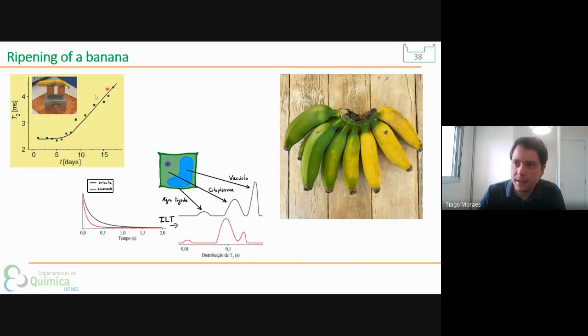First, the easiest way to analyze a sample with relaxometry is to think about the mean value of the relaxation times. For example, in this example, you see the ripening of a banana in function of relaxation times. As the biological change in the banana occurs, the relaxation times will change here in function of the days. So you can monitor and estimate some parameters from this.